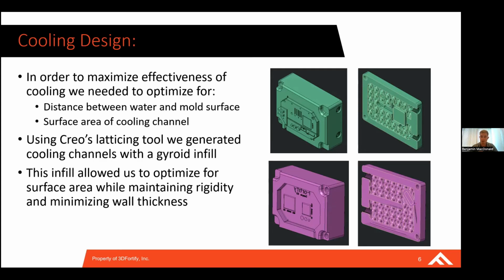So using that knowledge, we designed this lattice geometry, knowing that we're going to be able to maximize the surface area of our cooling channel, so we have more water coverage that's pulling heat directly out of that mold block. We're also able to reduce that wall thickness between the surface of the mold and the cooling channel. So we ended up using a 5mm wall thickness from the surface of the mold tool to the cooling channel. That's very important because minimizing that distance enables us to pull more and more heat directly from the surface of the tool. On top of that, we still had our structural rigidity with the lattice geometry.